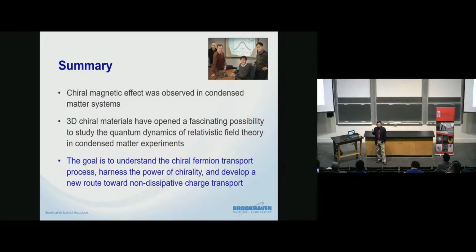And actually, this is the problem over there, because it's always scattering. The good news is that it's not regular particle scattering, right? That can just happen all the time, and it's very easy to flip it, to scatter. But for chiral particles, you have to change the chirality, okay? Because they are on separate Weyl nodes over there, it takes a large momentum transfer. Right? So that's why it's difficult to flip it. But it does flip, right?